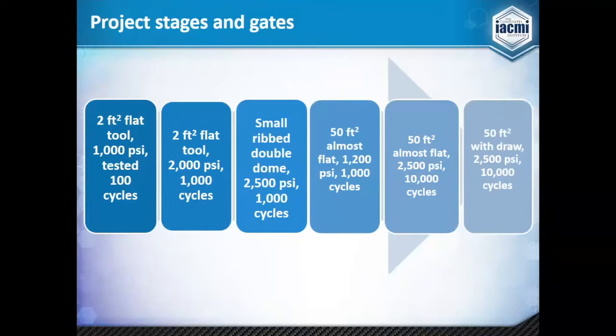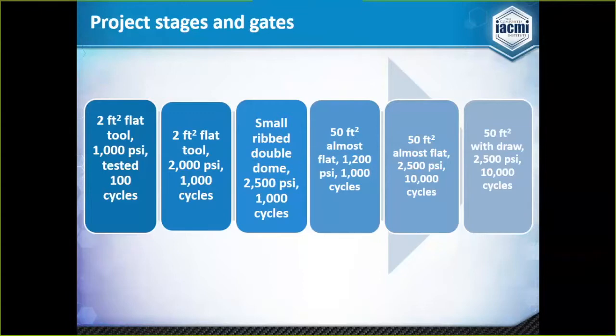at something that's a bit more complex, maybe a double dome shape or some other shape that we as the industry come together and say we need to do, but include some ribs and other features in that, and then again demonstrate that at similar pressures and cycles, and then move on up. Try to get on up toward that 50 square feet, and progressively test it at higher pressures, and then continuing on to longer cycles. At each step of the way, we need to understand what we need to modify, what needs to be fixed, what other features need to be added. So this is just a preliminary type of approach over a several year period to get there.